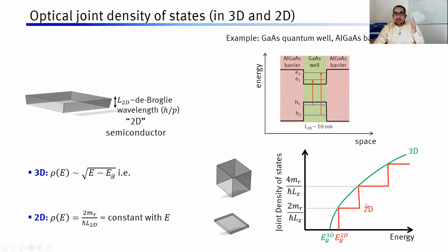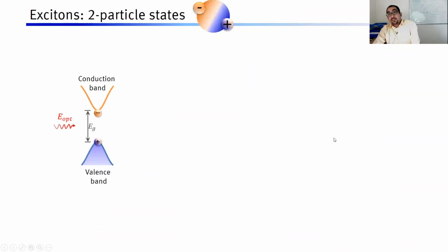So what do we expect? If we now measure some absorption spectrum for a 2-dimensional semiconductor, then we should expect a step-like behavior, because this is how the absorption will keep on increasing as the light is hitting more and more transitions, not resonances, transitions.